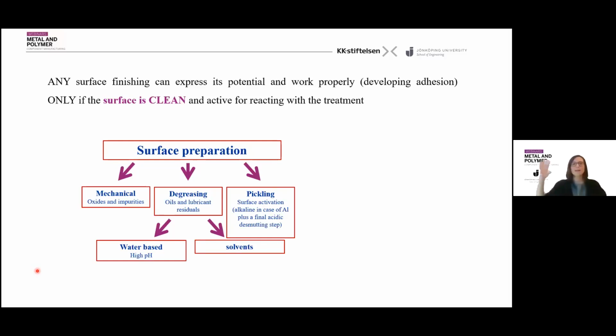Surfacing, this is the overall name, is made of many steps, and we have to combine different strategies to remove that complex surface state. We should apply a mechanical preparation to remove everything solid, like oxides or impurities, which also helps roughen the surface to increase adhesion. Then we apply a degreasing step where we use organic solvents or water-based soaps to remove everything organic in nature, usually oils and lubricant residuals from previous manufacturing steps.